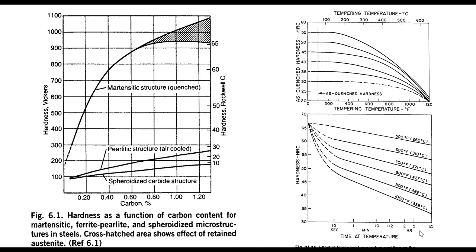When I temper it, I get a choice of the temperature or the time. The longer time the softer it gets, the higher temperature the softer it gets. The challenge is I really, until I get to 400 degrees Fahrenheit, I don't get any tempering. And from about 450 degrees to 900 degrees, it embrittles the steel. So I really want to, if I want the highest strength, I'm making knives, I temper it 400 degrees. If I want it to be a normal structural component, I want it to be tempered above 900 degrees, typically from 950 up to about 1250.